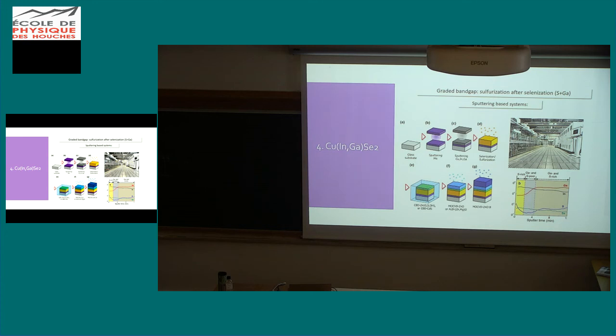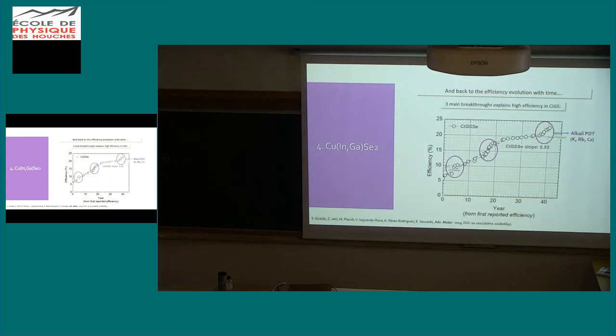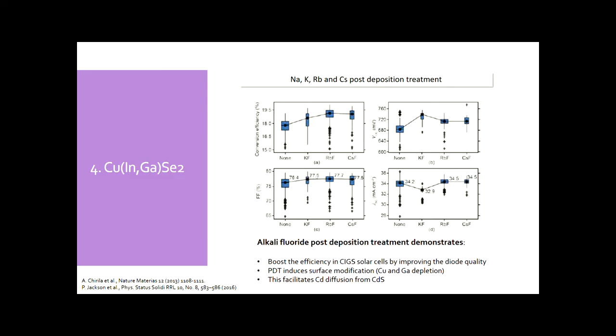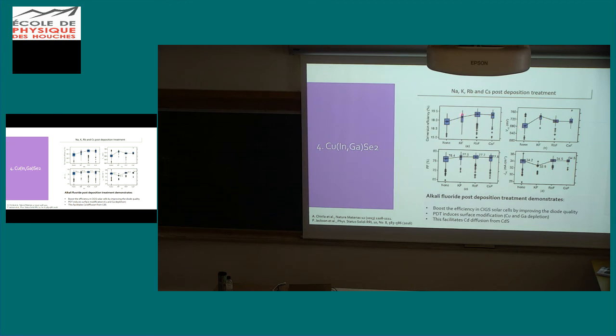for creating both gradings. And the latest progress was thanks to the alkali PDT process, basically treating the surface with a heavy alkali element. So this was one of the first reports on this, in this case between EMPA and ZSW in Germany, showing how using this potassium, rubidium and cesium treatment of the surface of the CIGS, the efficiency can be really boosted.